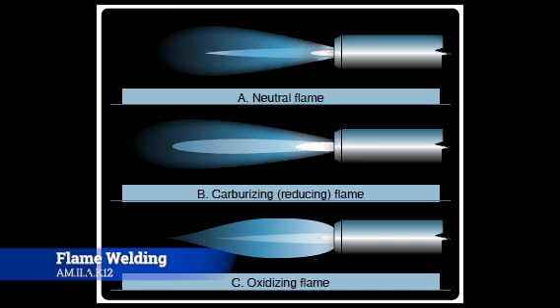Now, once you've got a flame going, you're going to have to make some adjustments. There are three types of flames that are commonly used for welding: the neutral, carburizing, and oxidizing, as seen here on this graphic. So the neutral flame burns about 5,800 degrees at the tip, and the inner luminous cone is produced by a balanced mixture of acetylene and oxygen supplied by the torch. The neutral flame is used for most welding because it does not alter the composition of the base metal. When using this flame on steel, the molten metal puddle is quite clear and the metal flows to give a thoroughly fused weld without burning or sparking.